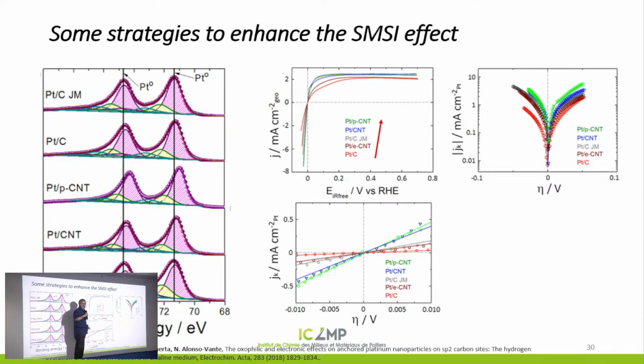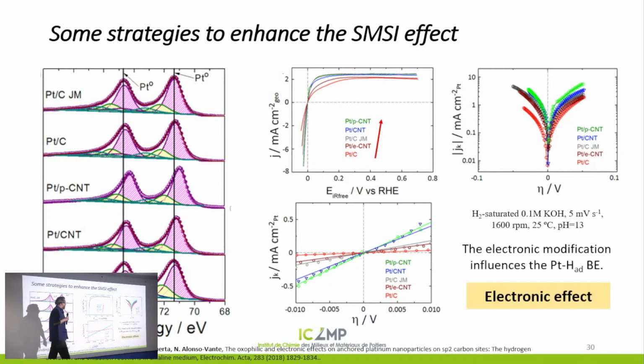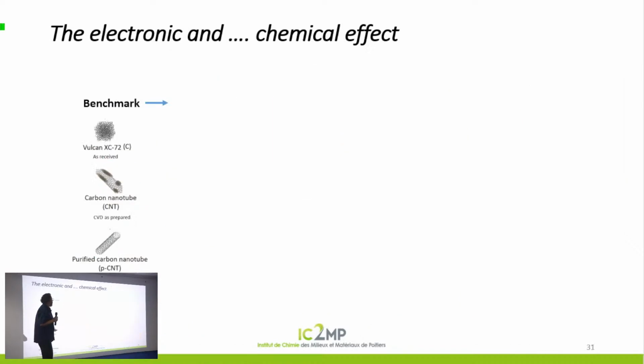That recalls that we are working with Ohm's law, okay? So the straight line gives you the resistance, and the slope delivers the conductance, because it's I over V or 1 over R. So if the slope is bigger, that means that the resistance is lower. The transfer resistance decreases because of the modified electronic property of the material. That is what we call the electronic effect. But is there more? Yes, there's more.